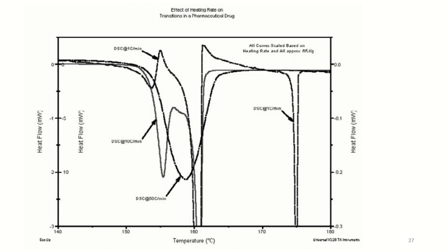Since it begins to melt near 153 degrees Celsius, as also seen in different heating rates like 1 degree Celsius per minute and 10 degrees Celsius per minute, we can see that the crystal form in the original sample is the lowest temperature one. The lowest temperature means it would be the least stable polymorph.